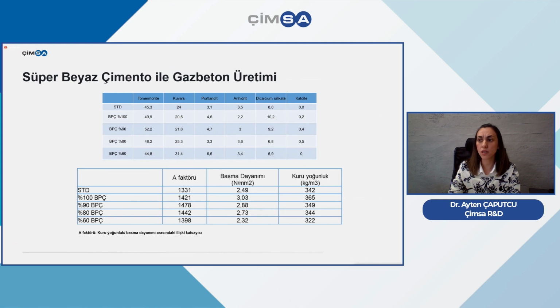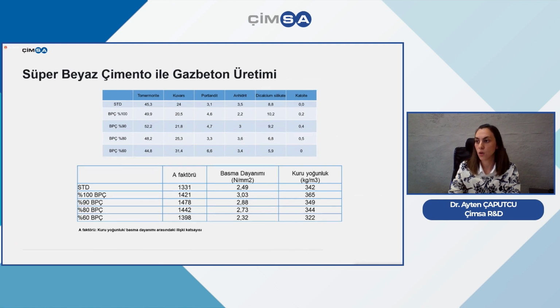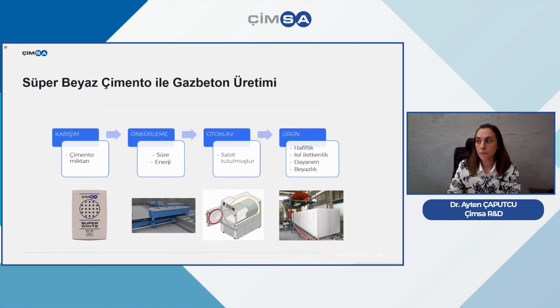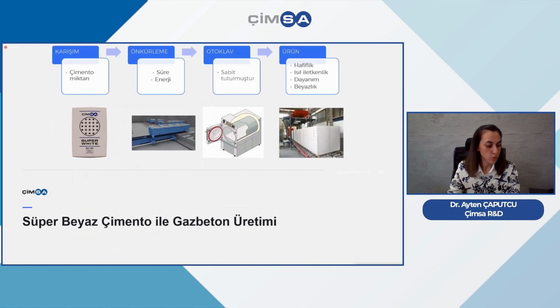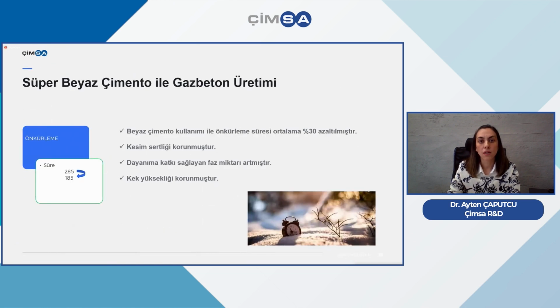As I told you, the tobermorite phase was important for us due to porosity and other properties. And we see here in the tables the comparisons between standard cement and white cement in the values of factor A and pressure resistance, as well as dry intensity. When we look at this study, we see that white cement used for AAC was yielding different results. So we wanted to compare and contrast this when we use white cement as a basis for AAC.